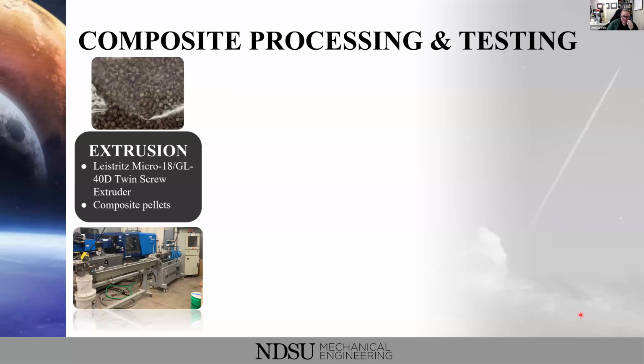So for our processing, we first did some extrusion. We're using an 18mm twin screw co-rotating extruder. It's made by Leistritz, a German manufactured extruder. And then at the end of it, we've got a pelletizer. So we did turn it into pellets before 3D printing with it.